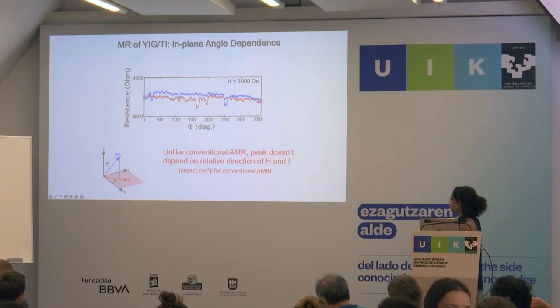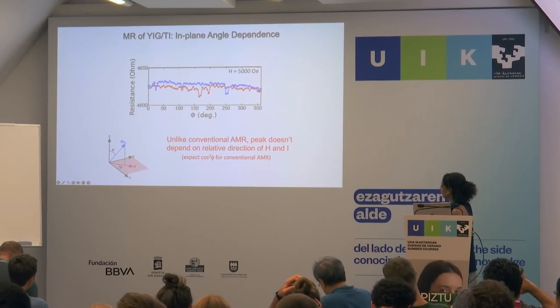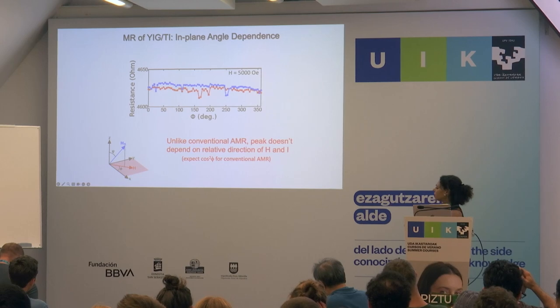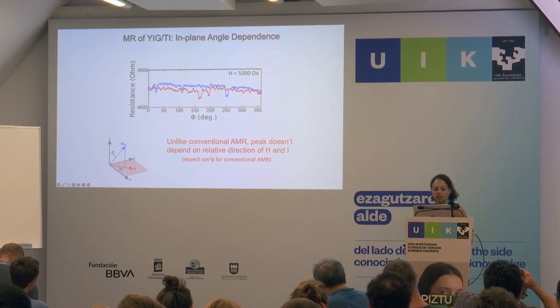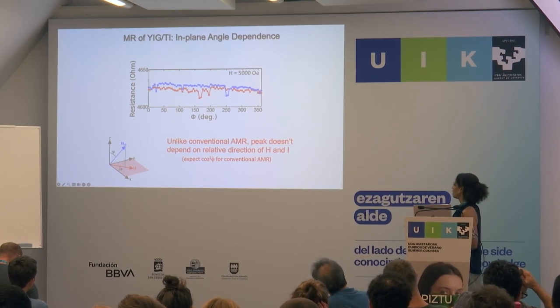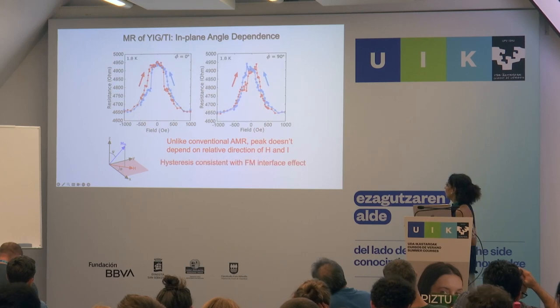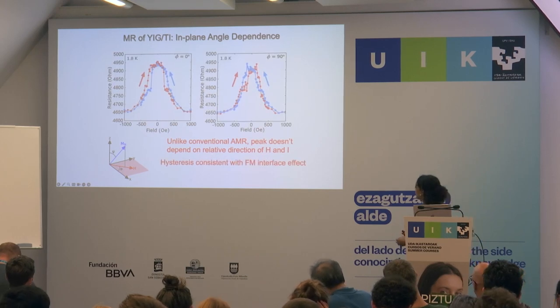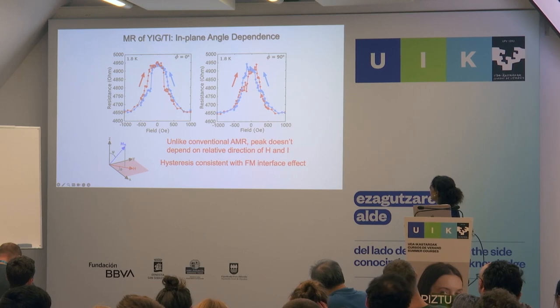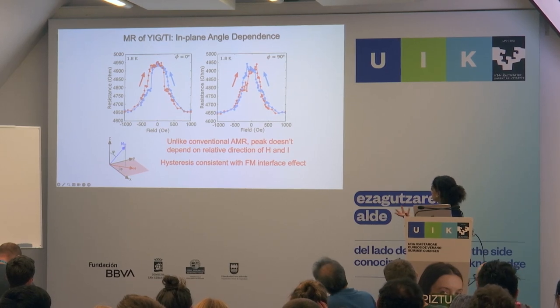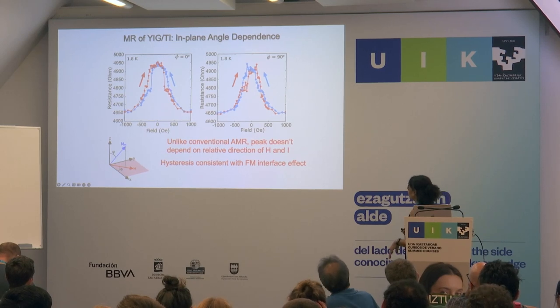This is the in-plane angle dependence. There is none. So unlike a conventional AMR peak, we don't have any dependence on the relative direction of the field and the current. So it's clearly not conventional AMR. You can see that it's both hysteretic and it looks the same in plane and out of plane. It looks the same at any direction in plane, 0 and 90 degrees.